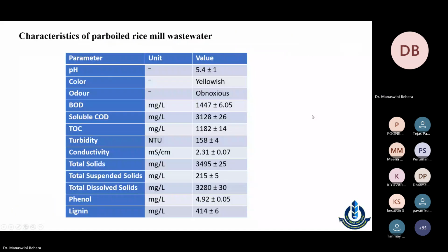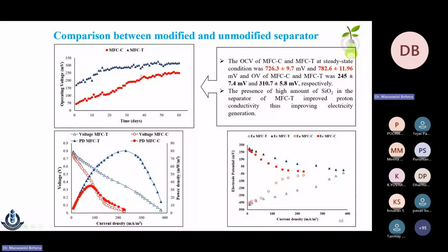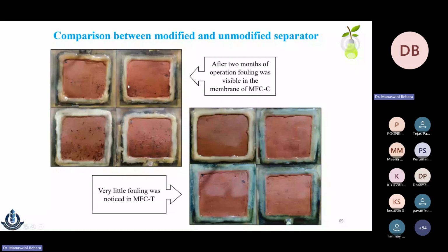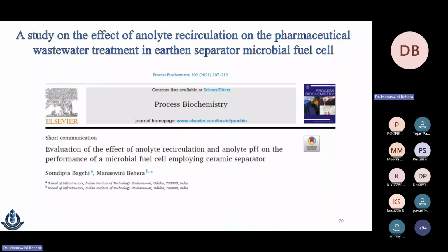So you can see here some results I will show you. Comparing the control MFC and the treated ones, where the membranes are modified, we could see better performance when we added rice husk. Membrane fouling, too, we checked after 2 months of operation. The membranes modified with rice husk showed very little fouling, so the cleaning frequency is minimized when we modify the membrane with rice husk for rice mill wastewater treatment. If some of you have seen parboiled rice mills, a very dark brown color wastewater is generated, which is very highly polluted, and it comes under the orange category of the Central Pollution Control Board. So it could be treated very effectively in the microbial fuel cell system with the generation of electricity.